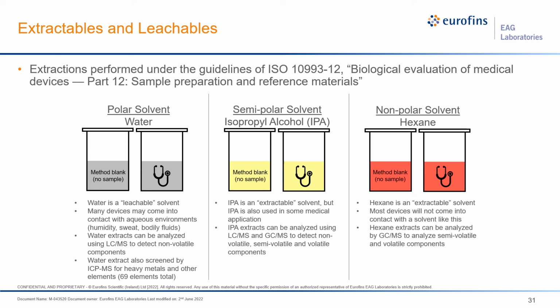When we perform these extractions, we follow the guidelines of ISO 10993 Part 12, Biological Evaluation of Medical Devices, Sample Preparation and Reference Materials. To perform these experiments, we use 3 different solvents that cover a wide range of polarity. We have a polar solvent, which is water, a semi-polar solvent, which is isopropyl alcohol, or IPA, and a non-polar solvent, which is hexane. If you've ever heard the phrase "like dissolves like," the same sentiment holds true here. Water, our most polar solvent, is going to be capable of extracting the most polar components from the polymer. Likewise, our non-polar solvent, hexane, is going to be isolating and extracting all of the non-polar components.